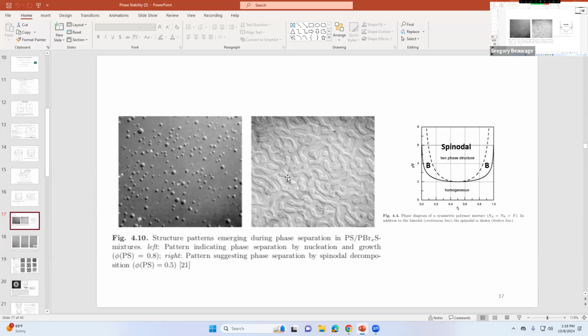So the separation distance between these phases and the size of the phases is roughly the same throughout the whole thing. Because you have a perfect size, that gives rise to, if you do a correlation function on this, so you take a point here, then how far am I until I get to another of the blob phase? So that's got a fixed distance. That means if you plot the correlation function, it's going to have a peak in it. And the Fourier transform of the correlation function is the light scattering.